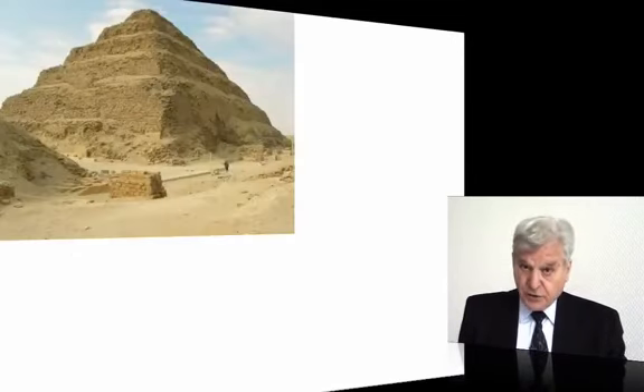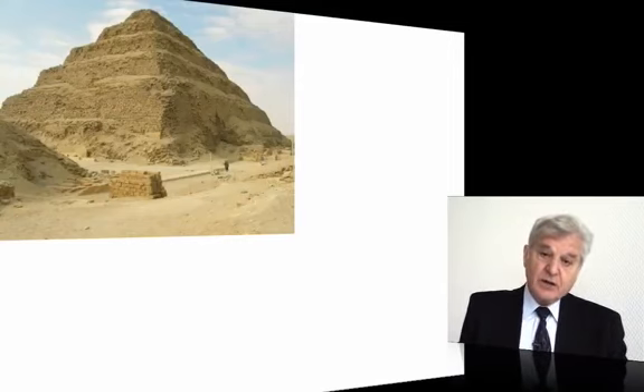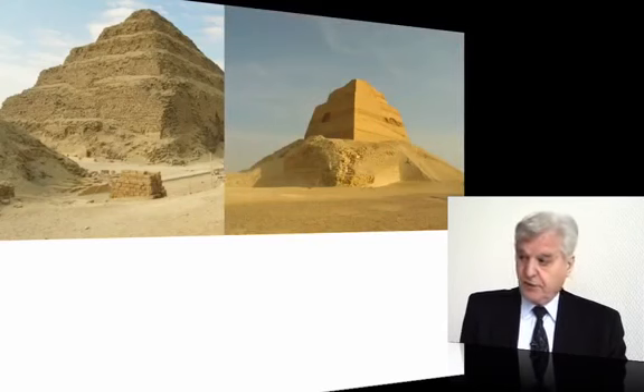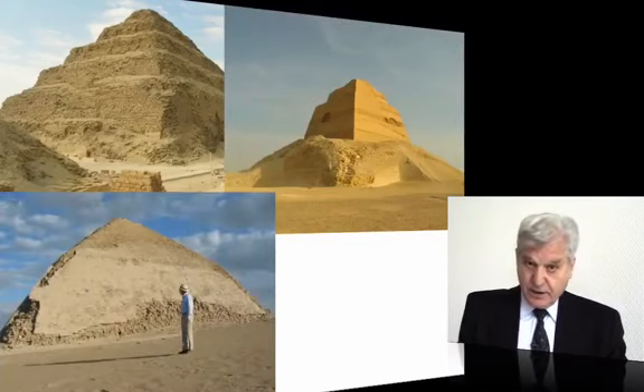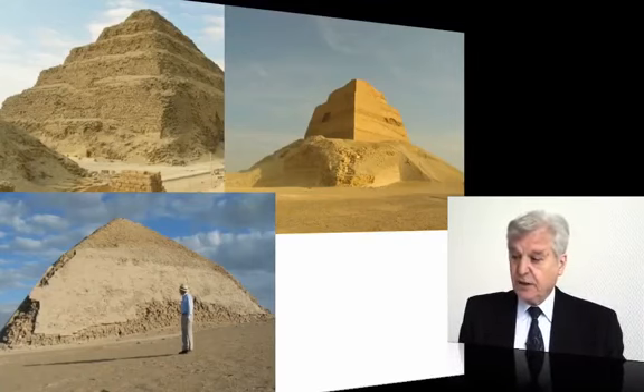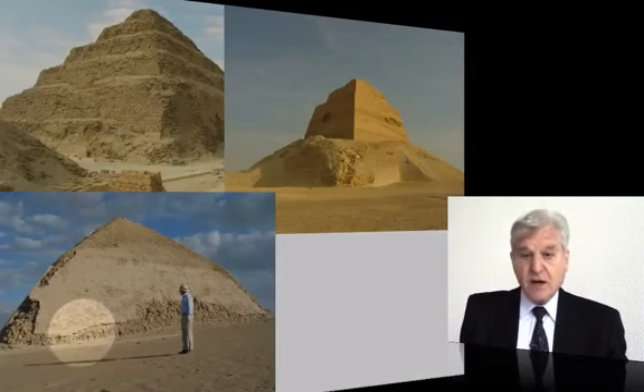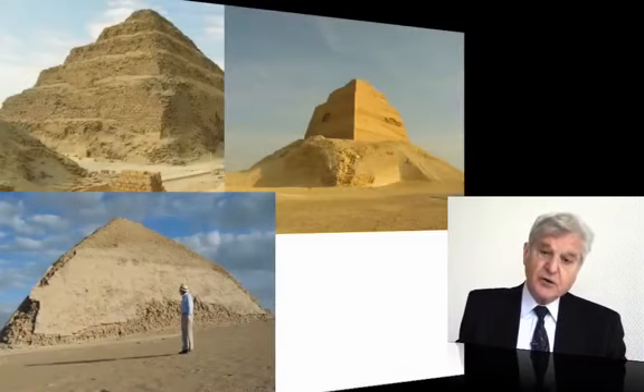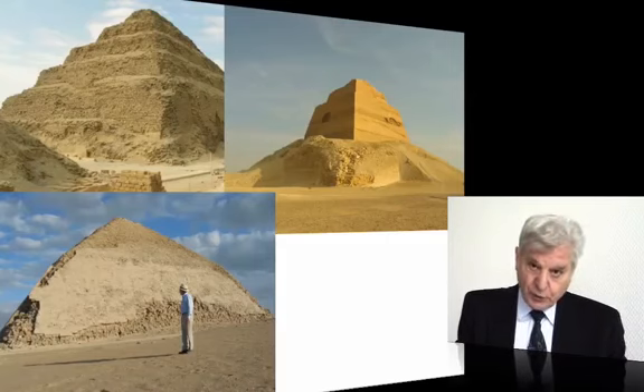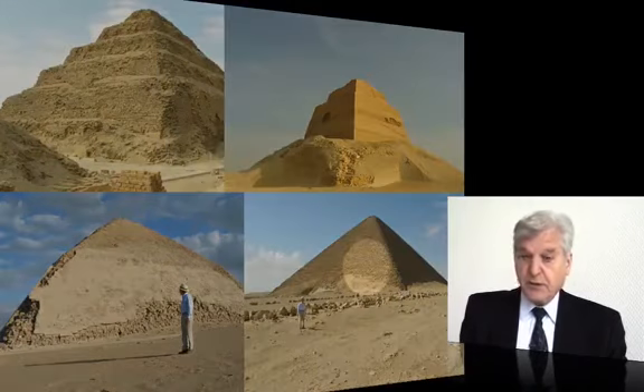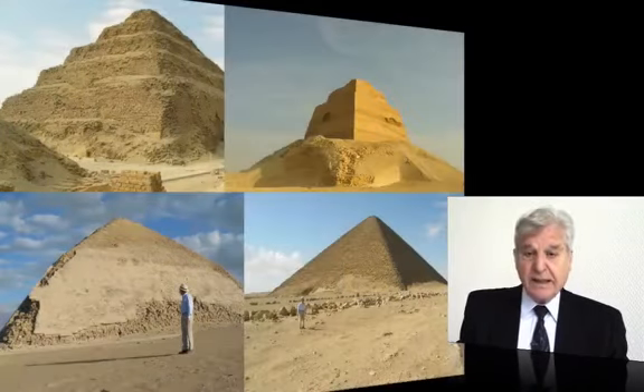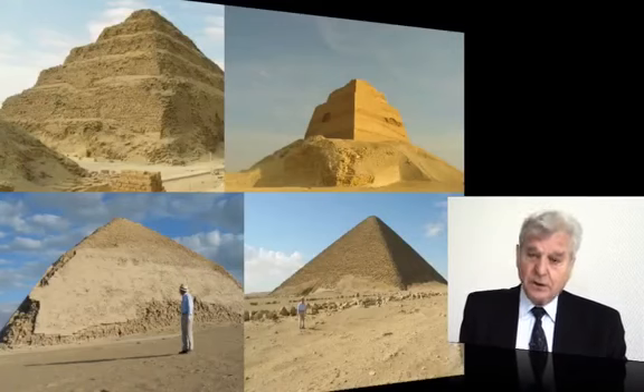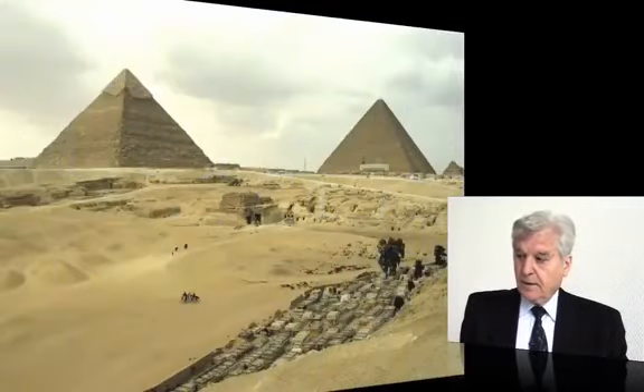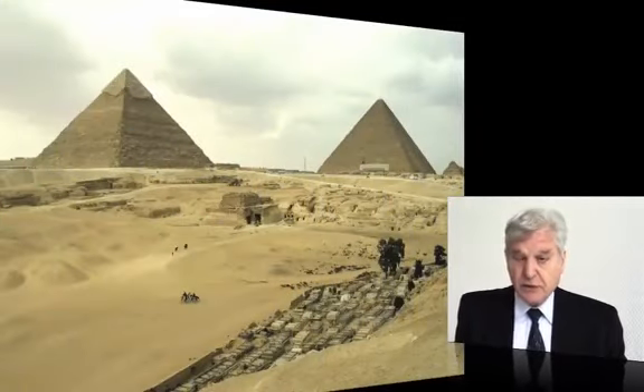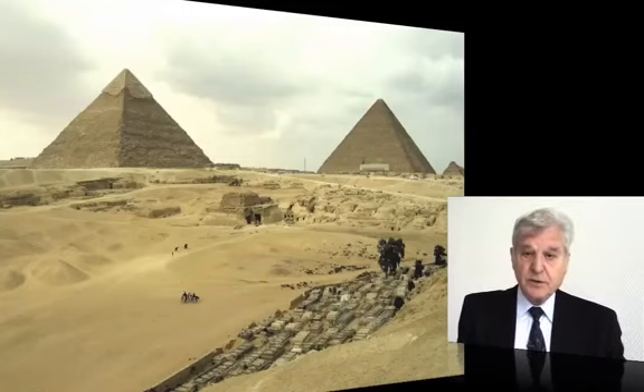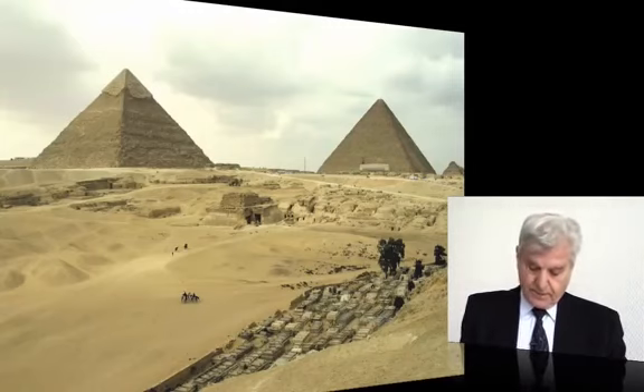So it started with the first pyramid in small bricks. They mastered the technology, improved the dimension of the blocks, and they ended with the first pyramid of Seneferu, that is the rhomboidal, where the blocks are still moved, still transported to the site, but they are becoming too big. And for the red pyramid of Seneferu, they are too big to be manipulated, and they are cast, they are pounded on site. We then arrive to the Giza plateau, where this technology was used for the Cheops, Chephren, and Mykerinos pyramids.